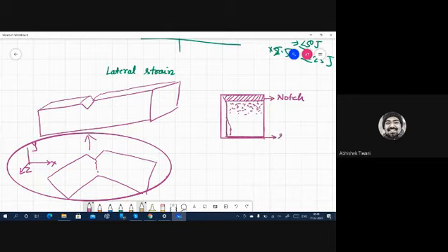So this region will be the shear lip region, and here you might have a complete flat fracture. So this would be the brittle part. This would be the fibrous or ductile part, but usually it will not happen that a crack will start with ductile and it will become brittle. No, it can happen. The opposite cannot happen.